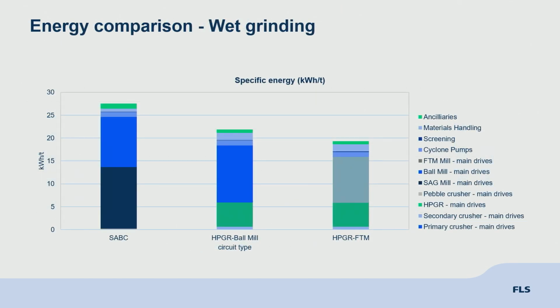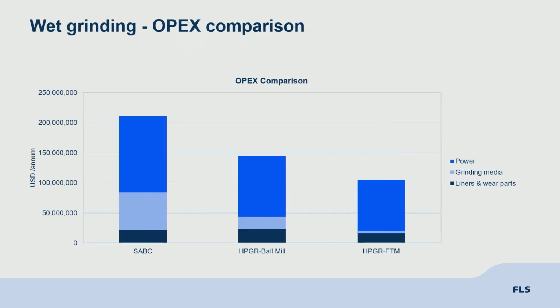So then when we dug into the wet grinding, we looked at an SABC circuit, which is your SAG ball circuit. We looked at an HPGR ball circuit, and then an HPGR FTM circuit to look at the specific energies and where the energy was being used within each of the circuits. And as you can see, it's stepwise in energy reduction throughout. And this lines up with an OPEX comparison that we also did.